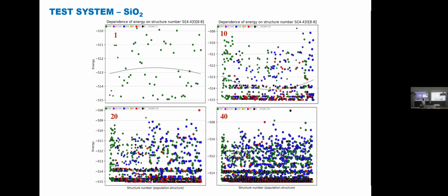represents a structure. Some structures have this energy of minus 15 electron volts, and then a lot of structures have bigger energy. But they are more or less in a small interval, like 5 electron volts. Then after the 10th generation, we see a bunch of good structures which have the lowest energy. Different colors mean that we used different methods to create the structure, like mutation, crossover, or a random structure. At the 40th generation, we stopped and we see a lot of structures here, and these are stable and metastable structures for this silica system.